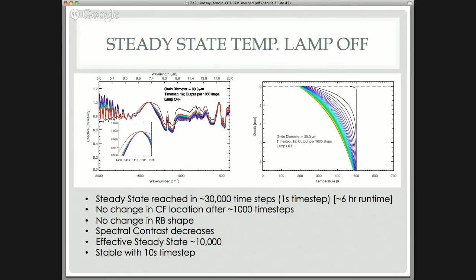You can see that it took about 30,000 time steps to reach that, and that's with 1 second time steps. Unfortunately, that's about 6 hours of runtime, which is not very tractable. But you can see after about 1,000 time steps, in this inset here, the location of your Christiansen feature doesn't move around very much, it stays in the same location. The shape of the Reststrahlen bands is not changing, but you will see a change in the contrast between the Christiansen feature and the Reststrahlen bands. If you look at the blue-green colors here and compare those for the emissivities, you're not seeing very much change in the emissivity. So we can call an effective emissivity at about 10,000 time steps, which is a lot faster in runtime than 30,000 time steps. And this is also stable in most setups with a 10-second time step instead of 1 second, which can really speed up the calculations.